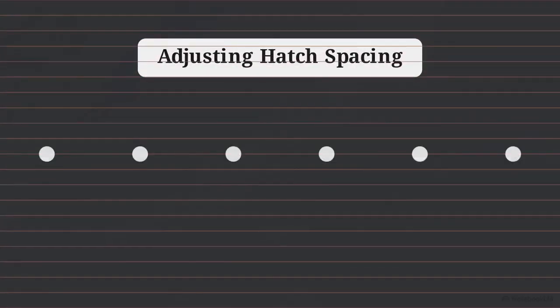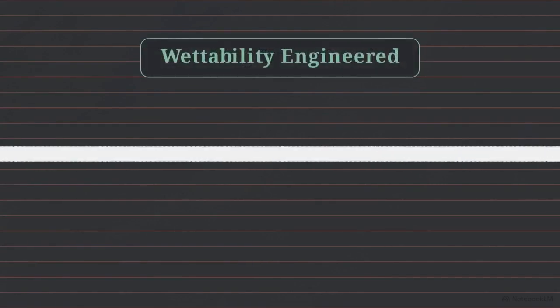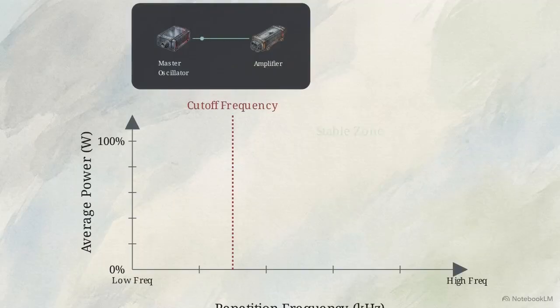By varying the hatch spacing and frequency, the laser alters a metal's wettability. It restructures the surface at a microscopic level to make it either actively repel or attract fluids. This degree of thermal programming transforms the surface from a static identifier into a functionally engineered component, optimized for specific industrial environments.